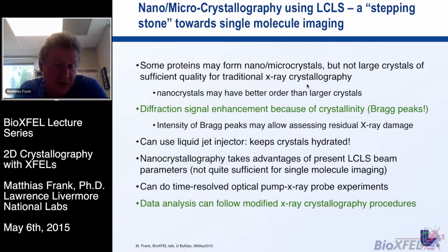Nanocrystals work well with the liquid jet injector because the Bragg peak signal is relatively large. You don't care too much about the water background. And the liquid jet injector, as I said, has the advantage that it keeps crystals and protein samples hydrated. It works very well with the present LCLS beam parameters, meaning the peak brightness that we have there, which is probably not quite sufficient for single molecule imaging yet. And there are methods developed in synchrotron crystallography, time resolved studies, and also data analysis developed for traditional crystallography, that can both be applied in nanocrystallography as well.